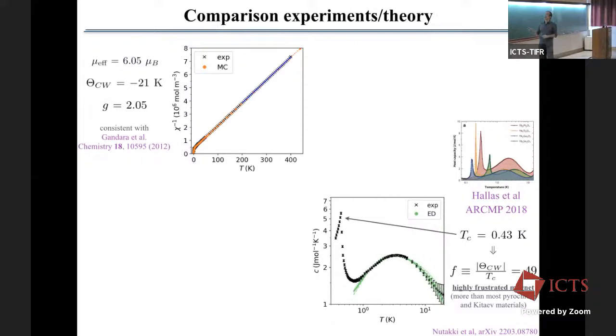Okay, good. And so we know it's well reproduced by just exact diagonalization of a single tetrahedron. Qualitatively, we can reproduce this bump with just ED of 4 sites of a tetrahedron with the parameters of this material. And so that's what we have done here with 5 sites, of course. And we can reproduce also this bump with 5-site exact diagonalization. So this is the first thing.